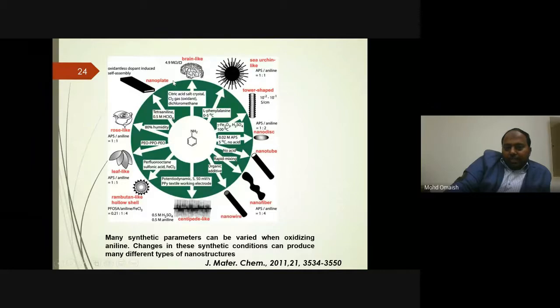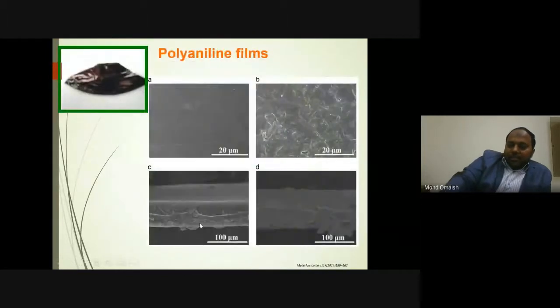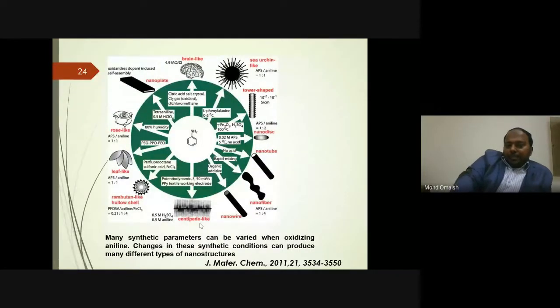There are a lot of experimental conditions which show different morphologies of polyaniline. For example, if you use ferric chloride, you can get a rambutan-like hollow shell. If you use N-phenylenediamine, you can get sea urchin. So by changing the oxidant, by changing the chemicals, you can get different morphologies of polyaniline. This is one of the very highly cited papers from RSC.